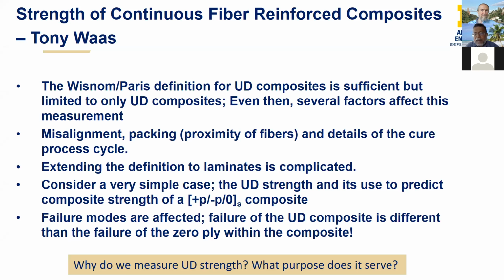In fact, in some cases, the 0 ply breakage is influenced by the adjoining minus P ply. In other words, if minus P is at 45 degrees, you may find that the 0 also failed close to the 45-degree line to the loading direction, suggesting that there is influence from other plies. Okay, so it's very important.